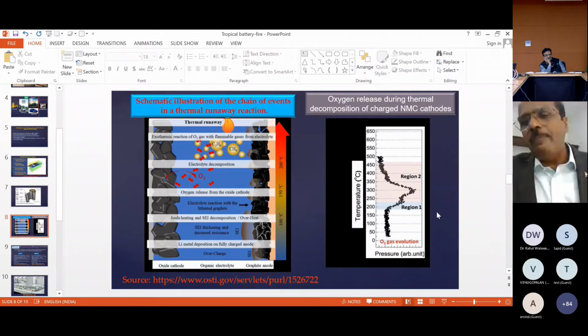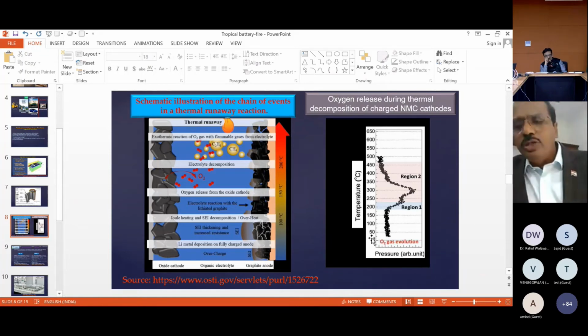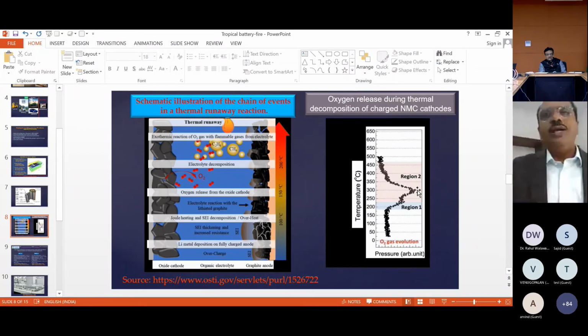If you see the right hand side, people intentionally did the experiment with the NMC cathode and saw how much oxygen is released. You can see that as the temperature rises, the peak on the right side shows how much oxygen is released, and around 250 to 300 degrees centigrade you have the maximum oxygen coming, and this oxygen is the dangerous one, what is helping it to blow up.